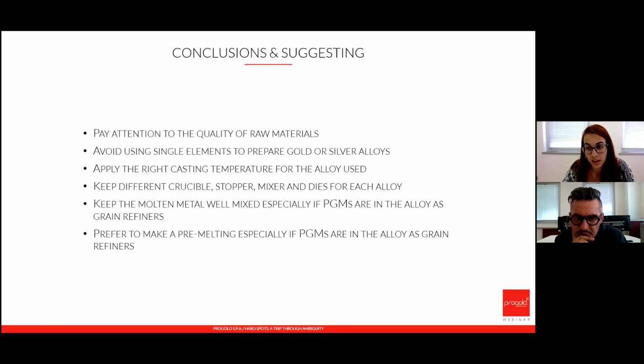The problem is that if you have investment casting, the investment reacts over certain temperatures. So if our metal is too hot, when it touches the investment, it's going to generate a series of reactions that are not going to generate hard spots, but are going to generate other issues. So we have to find a compromise in order to have a good mixing, but at the same time avoid these problems with the investment. So we go high to mix, and once we are convinced that the melt is mixed well, we go down with temperature to limit the reaction due to temperature when the metal comes in contact with the flask.